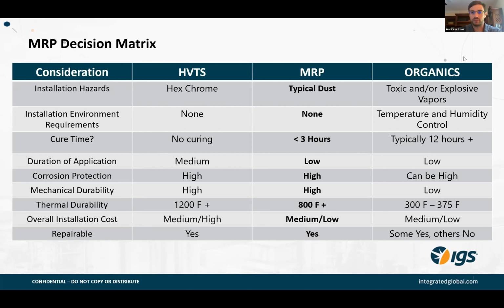The other is really the cost of controlling temperature and humidity. So in a local application, that's relatively easy, but in the larger vessels, that can be very expensive during an installation. With the MRP and the HVTS solutions, as long as you're not running water down the wall, you're not very concerned about the humidity in the atmosphere. So oftentimes, or pretty much all the time, you can eliminate the costs of requiring that temperature and humidity control, which can be very significant on some of these large scale options.